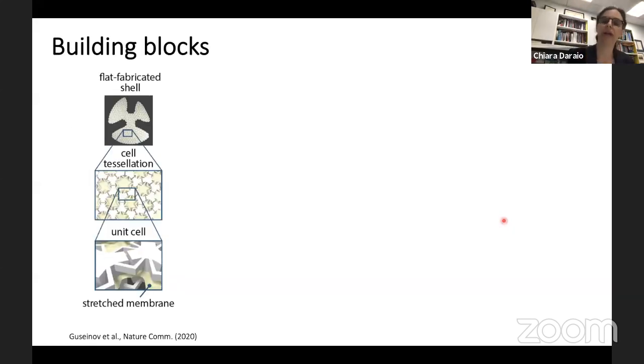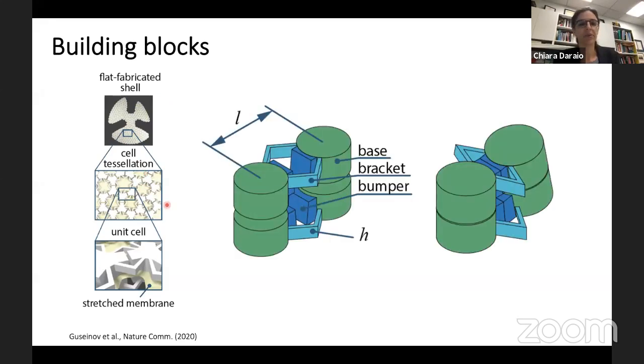So how did we do that? Rather than using the conventional design via homogenization, which in this case would not be sufficient because you really do need spatial variations and different properties in different areas, we basically fabricated a flat shell which has a tessellation of unit cells that are all different. And the fundamental building blocks of this unit cell that you see here, for example, in white, are reported in green on the central part of the slide.